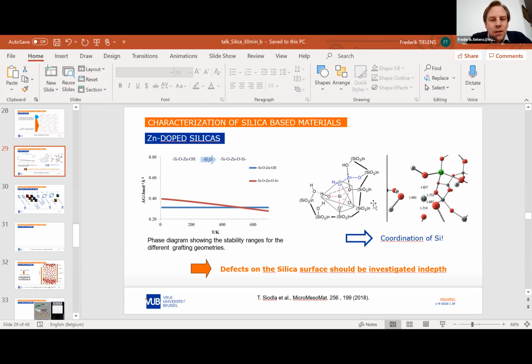Yeah, the one that you see here. Well, in fact, this is a kind of function. We don't calculate every structure at a different temperature. It's just a kind of extrapolation. We have the effect of the number of water molecules, so the stoichiometry, which you have as the two lines here, red and blue, and you also have the effect of the free energy we calculate here. We insert also the entropic factor, but this is only done for water, not for the solid. So it's an approximation.